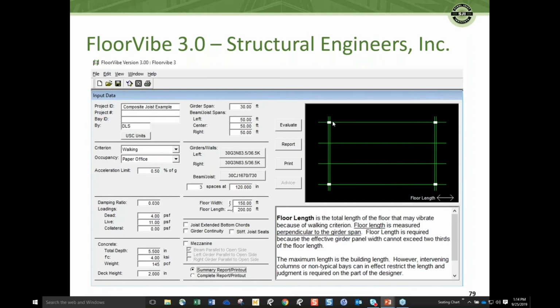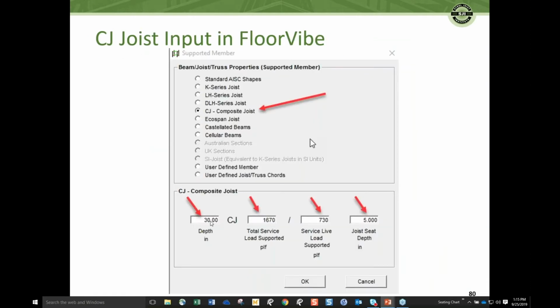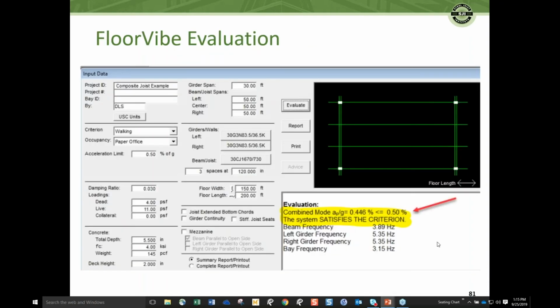This is just a screenshot from Floor Vibe 3.0. It shows some of the input parameters. You can put in the slab thickness and the loads. Actually, there's a special screen in Floor Vibe for composite joists where you can put in the depth, and the loads on this screen are service loads, not factored loads, so that's a key point to note. You can then calculate it, and in this particular case, the a_p over g was 0.446, which is less than the 0.5% g suggested for walking criteria. So this floor met the suggested vibration criteria.